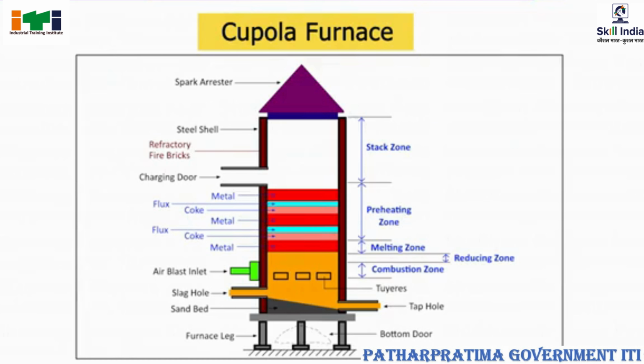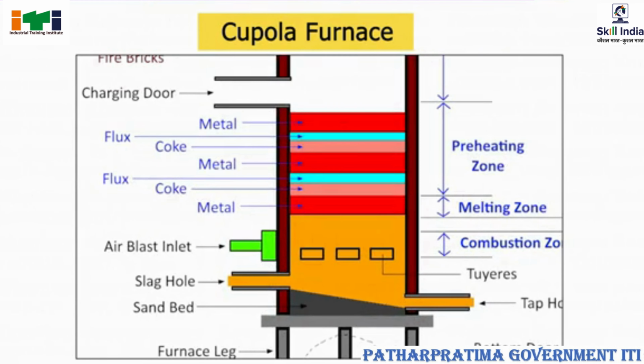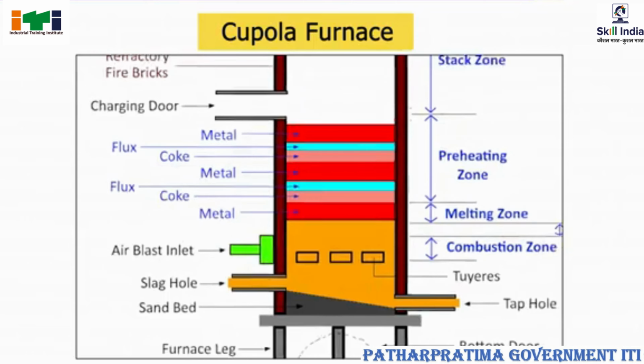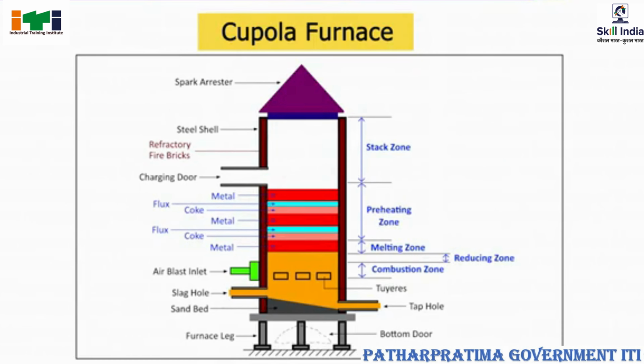After nearly 3 hours of burning, alternate layers of limestone, pig iron and coke are charged until it reaches the level of the charging door. At this time, the air blast is turned on to normal blowing rate and combustion occurs more rapidly in the coke bed. All oxygen from the air blast is consumed by combustion, and in the combustion zone, the temperature varies from 1150 to 1850 degrees Celsius. The portion of the coke bed above the combustion zone is the reducing zone.